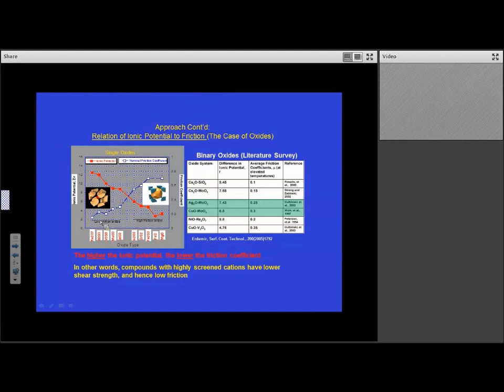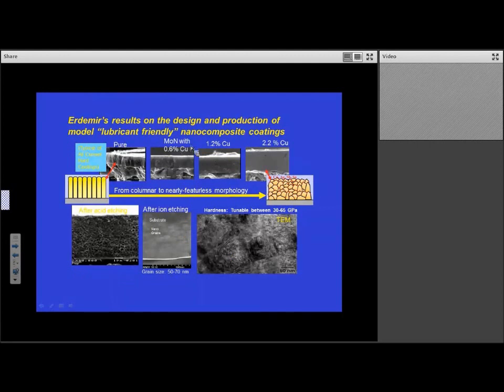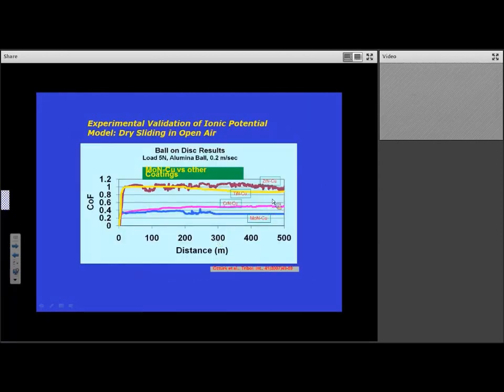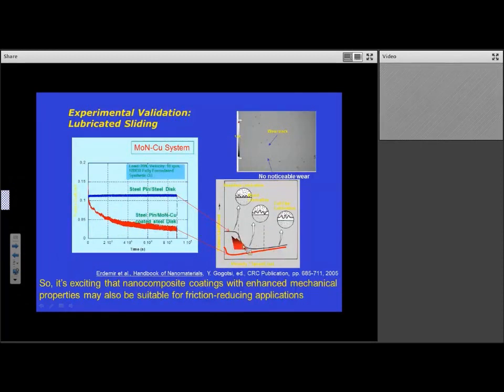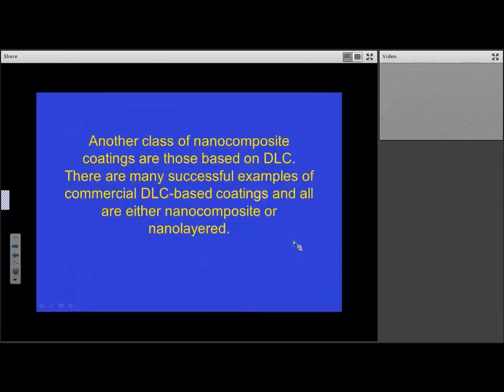These materials have increasing ionic potential and reducing friction. And just to say that one of the materials he looks at is molybdenum nitride with copper, and you can see a very dense structure. So I just thought it was interesting that he looks at it from a friction perspective, but we look at it from a wear perspective, but these materials still seem to be very promising. And you can see here increasing ionic potential and the best performance from that particular material here. Ionic potential increasing. And he explains it in terms of the effect on the Stribeck curve that this material can have. I'm sure, again, there's more work to be done in that area.